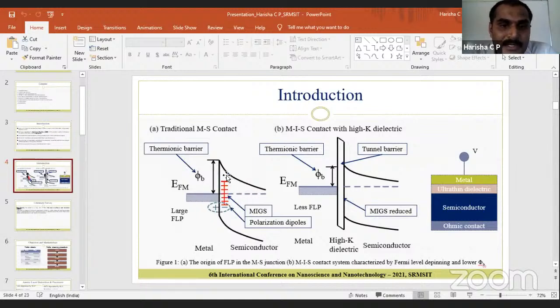So can it be due to the composition of the material? Yes, if there are any changes in the composition of the material, that is also one of the reasons people have observed. For that reason, we have used a very novel technique called atomic layer deposition, which will give you a very uniform layer. From a composition point of view also, it is a highly proven technique. The inhomogeneity may also be because of dipole moments at the interface, intrinsic and extrinsic dipole moments.